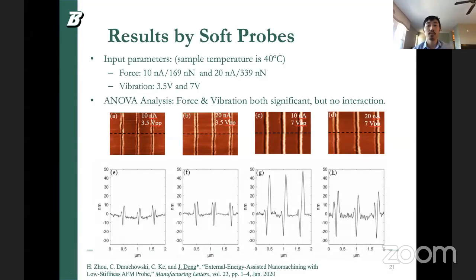So because of the integration of these two external energies, we applied different forces. We designed an experiment with two levels of force and two levels of vibration, with a constant sample temperature of 40 degrees C. As you can see, using almost 170 nanonewton and 340 nanonewton, we can see the trenches.